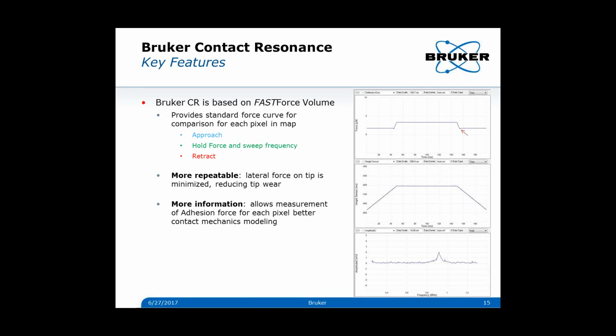We also get more information. We get the force curve and the adhesion from the force curve, so we can actually do better modeling. And we also get the whole sweep from the frequency sweep. So we are not trying to detect where the peak is by looking at only a couple of data points. That gives us better Q measurements and also allows us to detect artifact peaks.